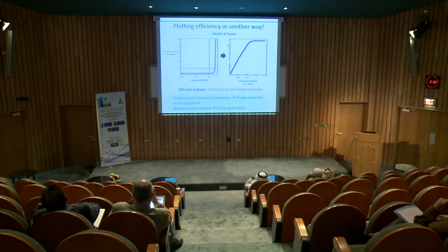So to look at charge extraction, we plot the efficiency in another way. Basically, we first measure the dark current, and then we measure the current under illumination, and then we subtract the dark current. So now what we look at on the left-hand side curve is truly the photocurrent density as a function of applied bias. On the right-hand side plot, we plot the photocurrent density as a function of effective bias. It means the bias that allows it to extract carriers, so the driving force for charge extraction, basically.